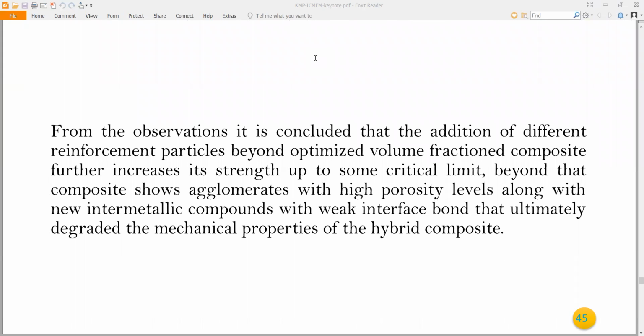So we can see from the observations, it is concluded that the addition of different reinforcement particles up to the optimized volume fraction further increases the composite's strength up to some critical limit. Beyond that, composites show agglomerates with high porosity levels along with new intermetallic compounds with weak interface bonds that ultimately degraded the mechanical properties of the hybrid composite.